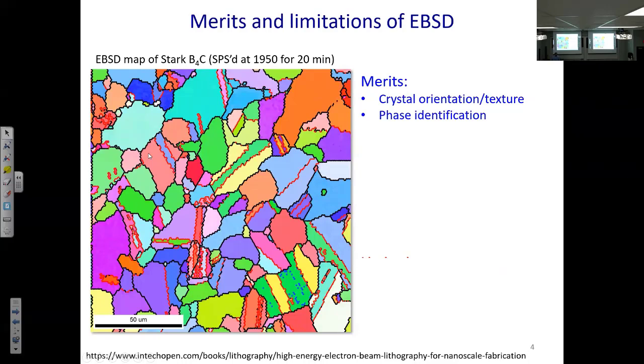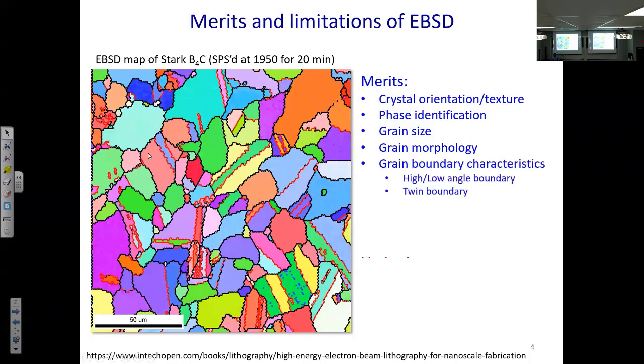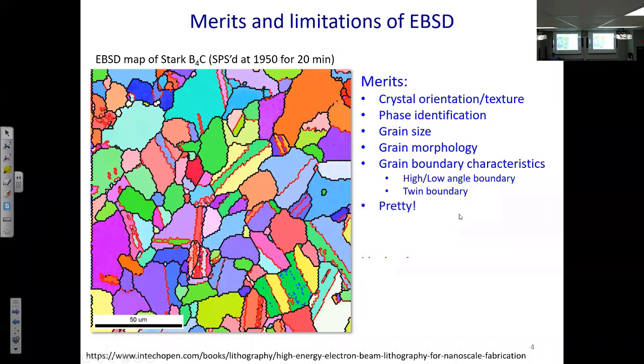The second type of information from EBSD is phase — for example, in a duplex steel with FCC and BCC phases, EBSD can map which regions are which phase. You can also study grain size, with modern software producing grain size distributions and histograms. EBSD provides grain morphology — whether grains are elongated or equiaxed — and grain boundary characteristics such as high-angle versus low-angle grain boundaries with different degrees of misorientation, as well as special twin boundaries that behave like mirrors. One bonus advantage: colorful EBSD maps tend to attract attention in publications.